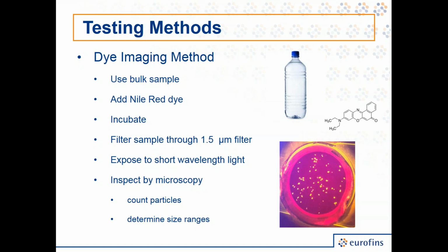So for example, inorganic materials like grains of sand won't be dyed by this chemical. And to a large extent, other matter you'll find, like pieces of water bugs or crustacean shells, also won't be dyed. It's not perfect, but it does a pretty good job. We then let the sample incubate for a little while with that dye, to make sure it absorbs really well onto the particles. Then we'll do a filtration step. And here we're using a 1.5 micron filter, so we're capturing everything larger than that. But there's no reason you couldn't use a larger pore size filter or a smaller pore size filter, depending upon the nature of your study.